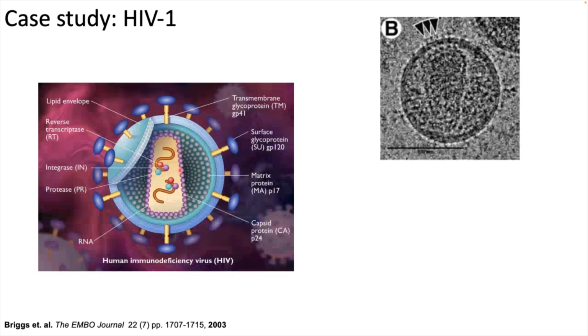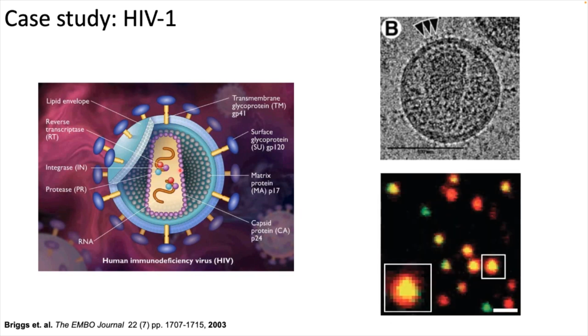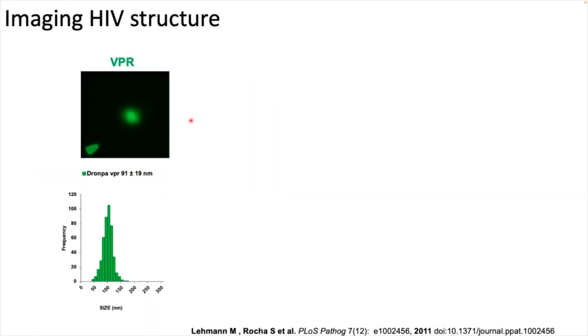And we know that the structure of the virus is like this from electron microscopy images. But when we put them on the microscope and we label two different components of the HIV particles, you actually see that they all look the same, just diffraction limited spots. But if we then do super resolution, and here we labeled different proteins with either a fluorescent protein or with an antibody that was then coupled with an organic dye.